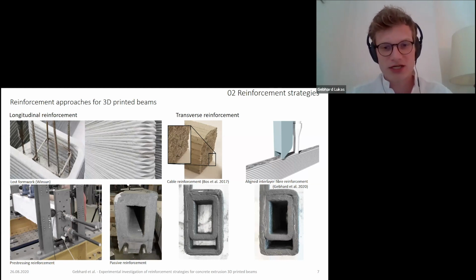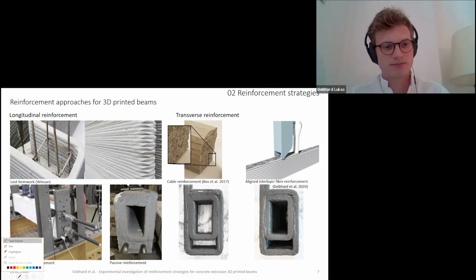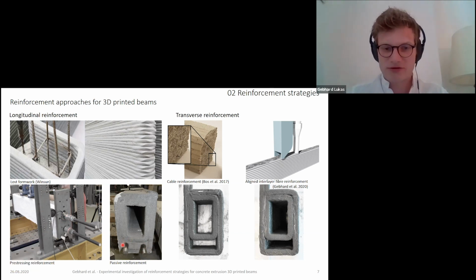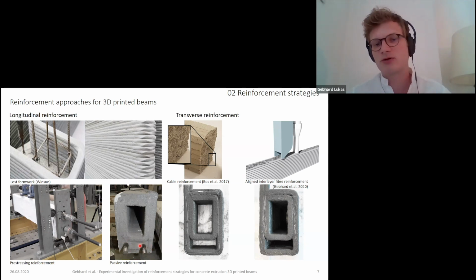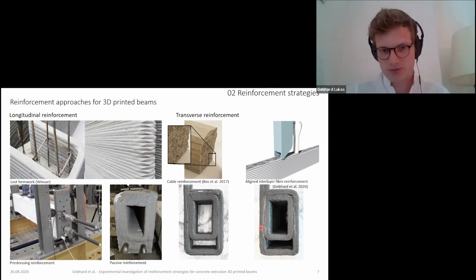Here, just a quick introduction of the reinforcement strategies, and afterwards I will introduce in more detail how we did these tests. So we did have one series where we used unbonded post-tensioning, which was achieved by these threaded rods that you can see here. And then we had conventional reinforcement, so conventional passive reinforcement, which was placed after printing in these voids down here and then grouted. And the two transversal reinforcement approaches, one was cable reinforcement and the other one the aligned interlayer fiber reinforcement.